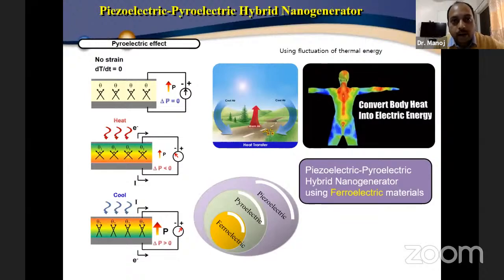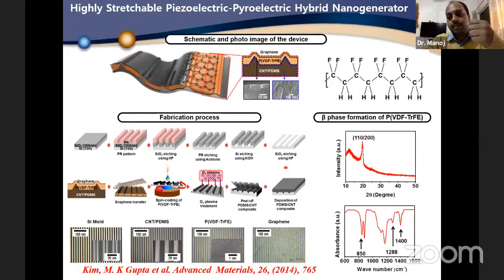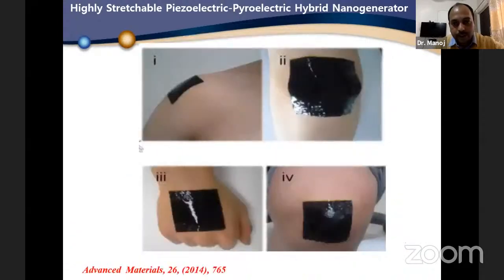In parallel, we have also developed stretchable devices. The device you can wear. To do that, we utilize PVDF polymer as the active piezoelectric material, graphene as a top flexible as well as stretchable electrode, and carbon nanotube as a bottom electrode. By the lithography technique, we have done this study. You can see, you can apply it anywhere.